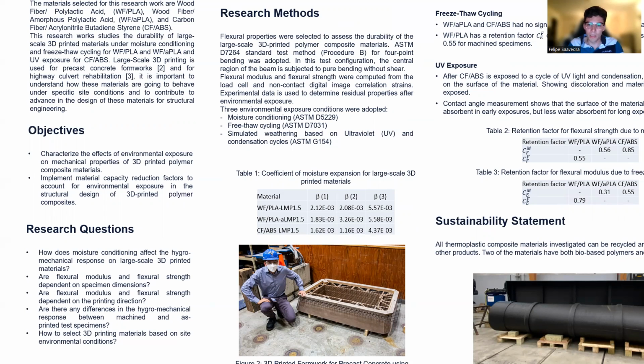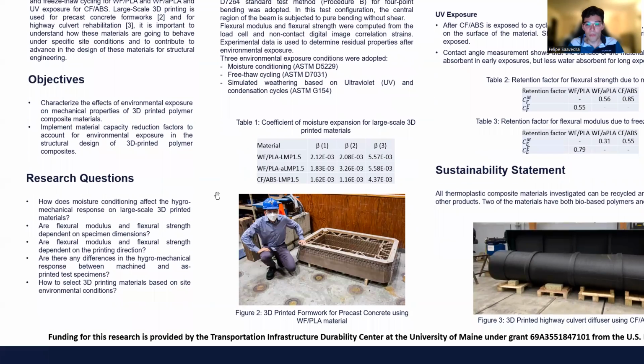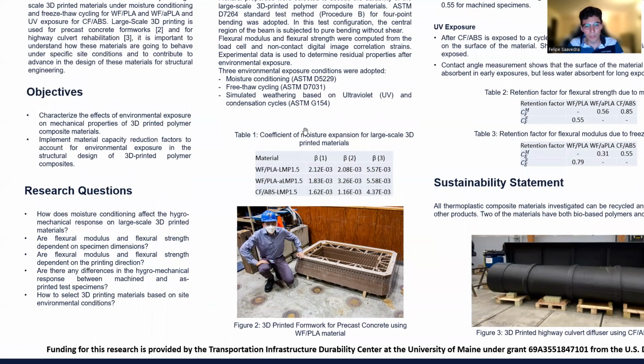polymer composites. The research questions for this work are: how does moisture conditioning affect the hygro-mechanical response of large-scale 3D printed materials? Are flexural modulus and flexural strength dependent on specimen dimensions? Are flexural modulus and flexural strength dependent on the printing direction? And are there any differences in the hygro-mechanical response between machined and as-printed test specimens? And the last question is how to select 3D printed materials based on site environmental conditions.